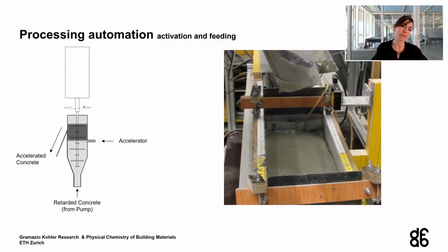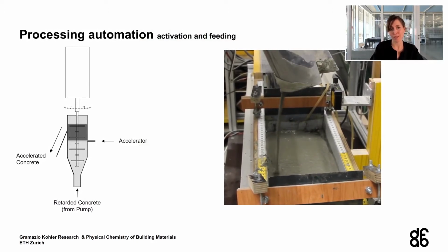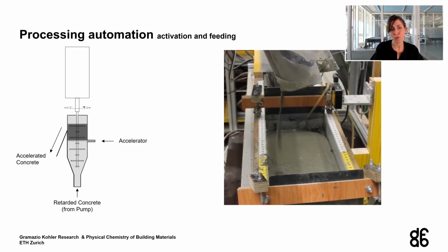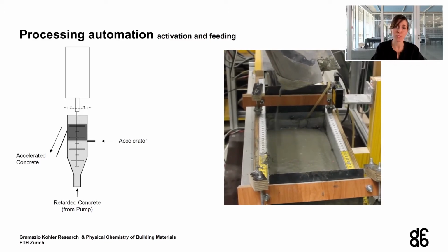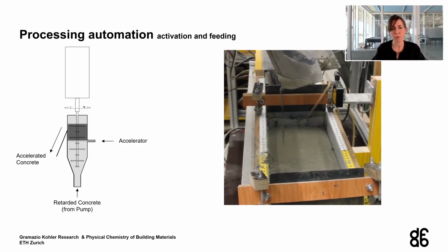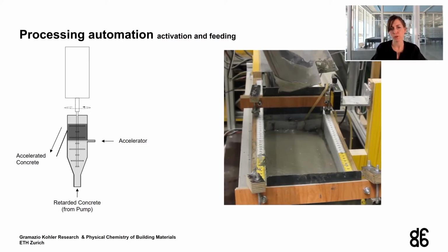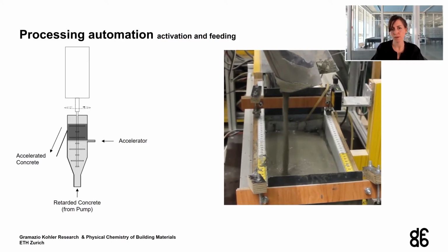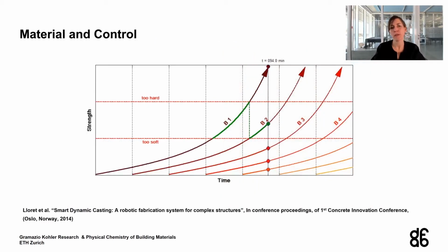However, changing the cross-sectional area, of course, made it difficult to follow up with the manual acceleration and mixing. Therefore, together with Lex Reiter and a group of students, we developed the concept of a process automation where we used a funnel in which the retarded concrete was pumped in from the bottom and accelerating admixtures were placed inside, and the material was flowing over as a self-compacting concrete into the mold. And of course, all of this at a speed that assures that the batches could sustain their own weight throughout the production.